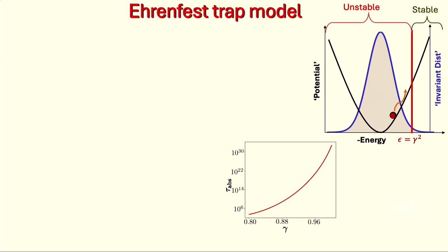So here is now the system that I'm going to look at. I have a random walk in a confining potential, but the axis here is energy. So I'm making a random walk in energy space, and then if I'm applying a strain of a certain amplitude, it corresponds to the system being stable only for large enough energies. I've flipped the sign here. So these are deep minima and these are shallow minima.